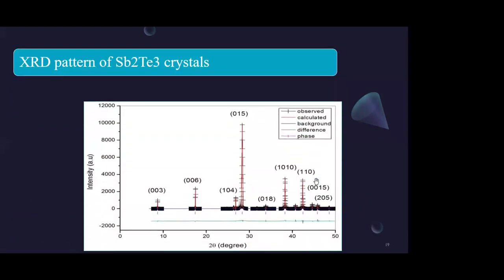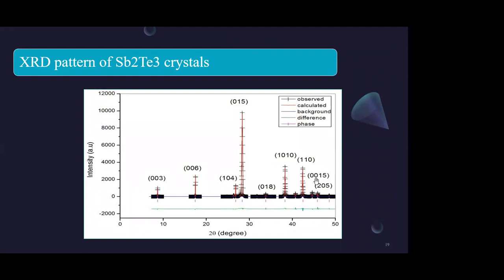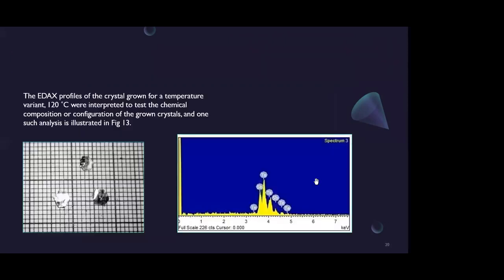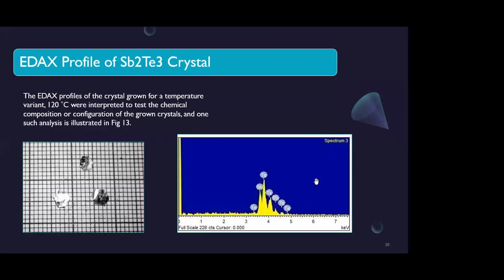But when I looked at the XRD pattern of the Sb2Te3 crystal, a peak was shown. You can see the intensity variation with the inclination with the 2 theta. Here the EDX profile of the Sb2Te3 crystal, which was grown at 120 degrees Celsius, was quite satisfactory. It was showing clear details that there was no oxygen content, and the chemical composition and configuration of the grown crystals were almost matching with the standard criteria.